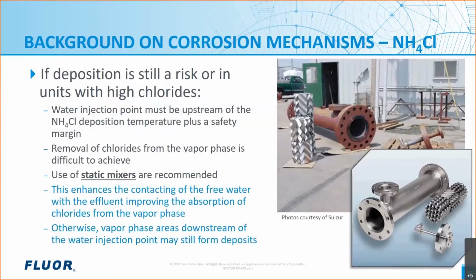So if there are units that still have a risk of the ammonium chloride deposits, one of our steps is we do realize you have to have the water wash upstream of the ammonium chloride deposition temperature plus the safety margin. And then to help remove all the chlorides from the vapor phase, we've found that any use of spray nozzles, we couldn't get there. Even the best quality spray nozzles, the finest droplet sizes, they still coalesce too quickly to really say that we've effectively stripped the chlorides out of the vapor phase.